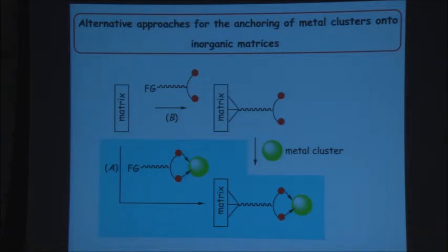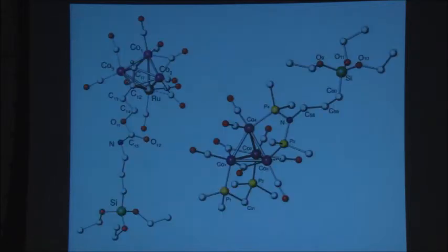You have basically two approaches available to reach that goal. One is to start from the matrix, and you react the matrix with a cluster already decorated with a functional group, and then you condense the functional group with the OH on the surfaces. That approach, called A here, requires that you can make such clusters, which have already been pre-functionalized. And that's exactly what is shown here. Just to give an example, you can have here a cobalt-4 cluster with a ruthenium here, and an alkyne, a CC triple bond initially, linked to this attachment here to the silyl group, which contain the OR functions. Or here a tetrahedron with cobalt-4, and again, at the end of this diphosphine, you have this alkoxysilyl functionality. So a pre-functionalized cluster can be made. So that approach can be a valid one.